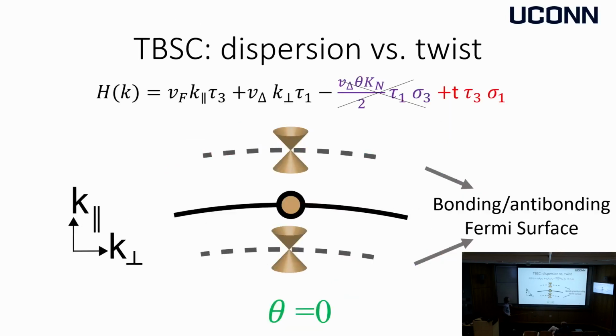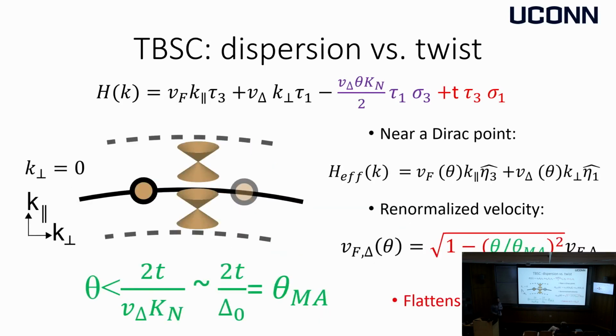At 0 twist angle, what happens is that you hybridize the 2 layers, and you get a bonding and anti-bonding Fermi surface, and basically there are Dirac cones where the nodal direction crosses those bonding and anti-bonding Fermi surfaces. And those Dirac cones are more or less equivalent to the ones found in individual single layers. Something interesting happens when you turn on the twist. Those Dirac cones come closer together, and the velocity of those Dirac cones is renormalized, and you can see that it goes down, and there's actually a special value of twist angle where it's supposed to go to 0.